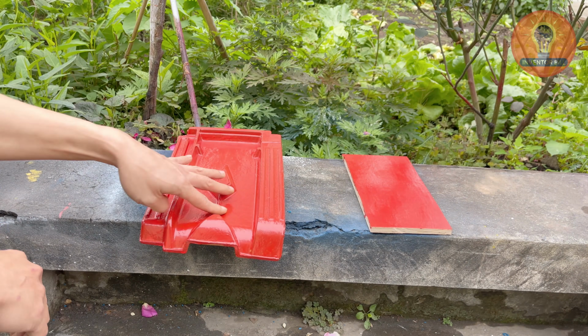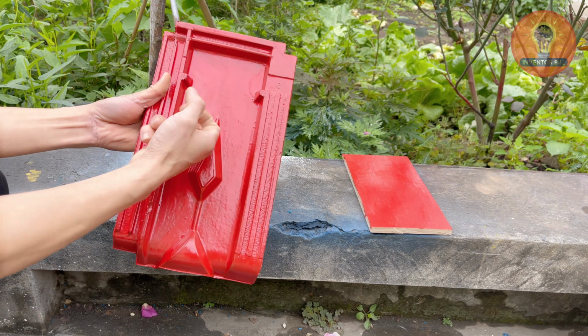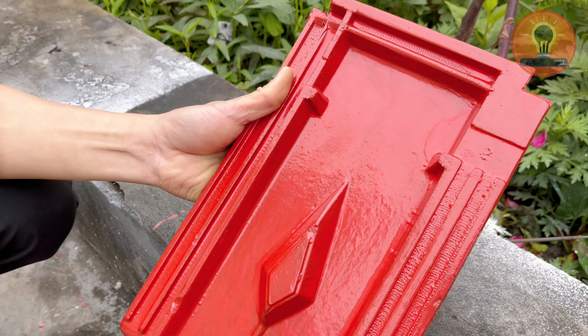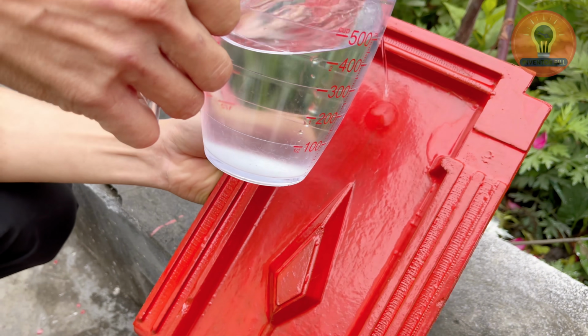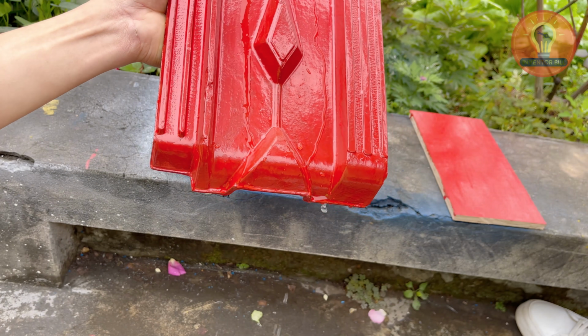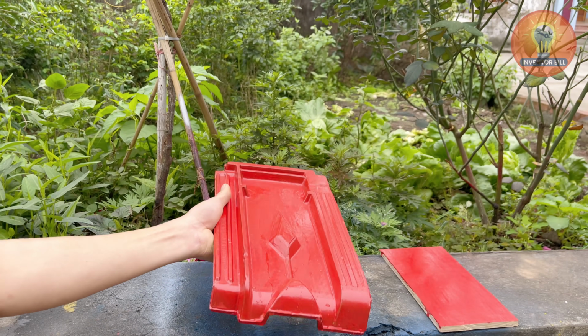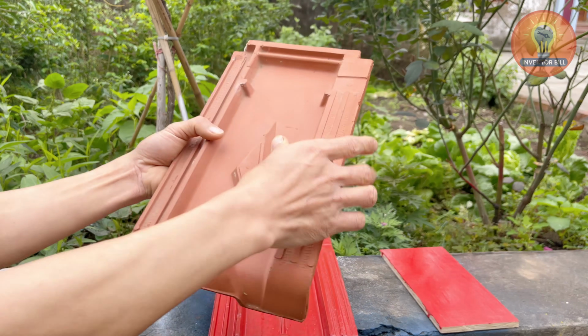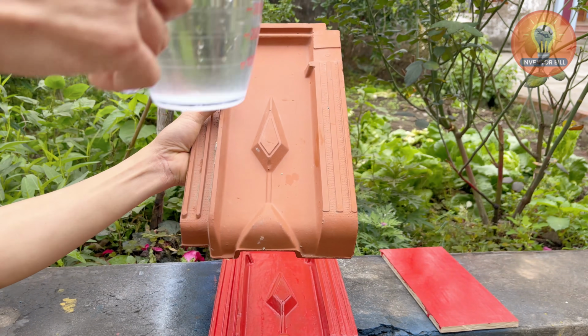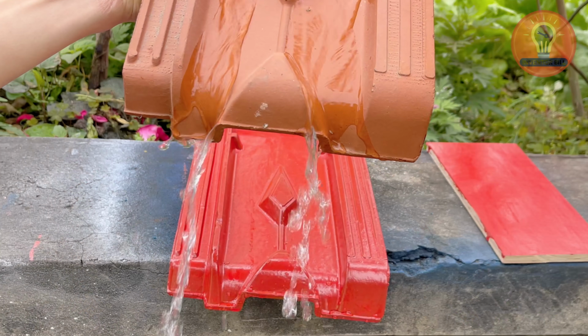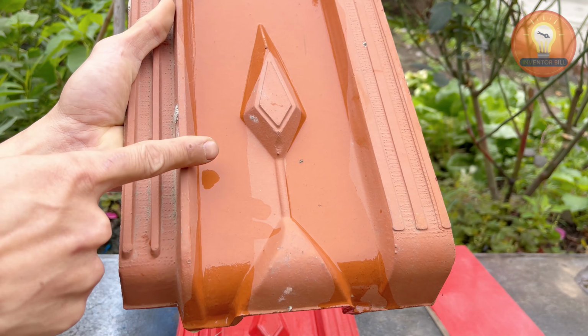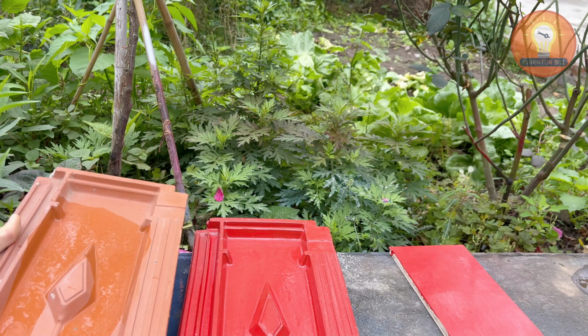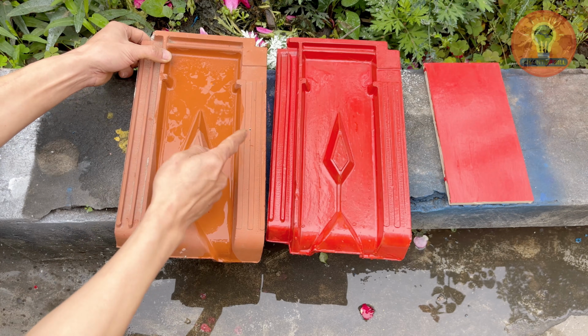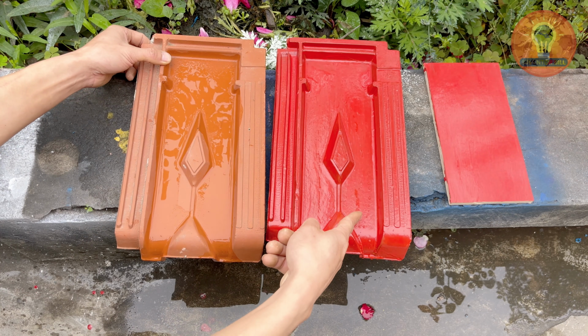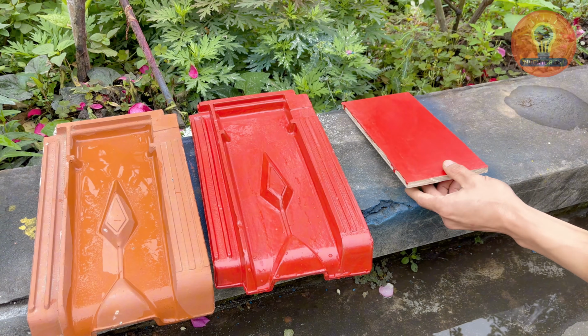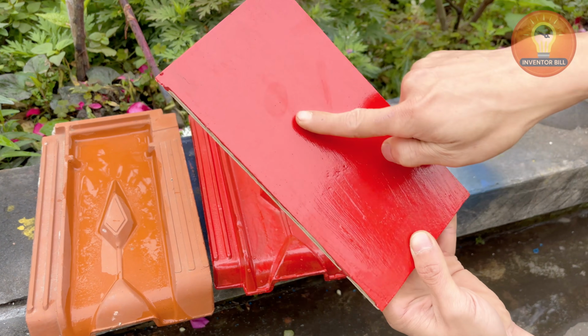Finally, return to the coated tile and wood. The surface has dried. The color looks even, smooth, and solid. Pour water over the tile. It runs off cleanly. No absorption, no darkening. Pour water on an untreated tile next to it. The difference is clear. The untreated surface absorbs moisture, while the coated one resists it completely. Do the same with the wooden board. Water beads on the surface. It doesn't soak in. The coating protects the material underneath.